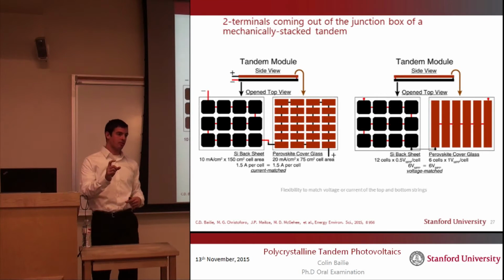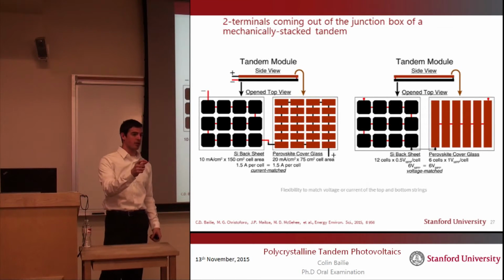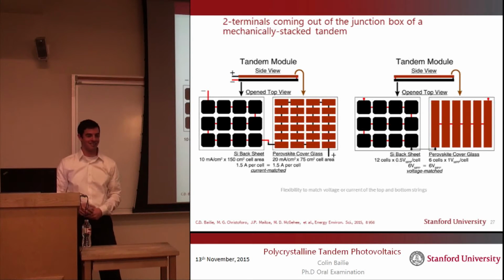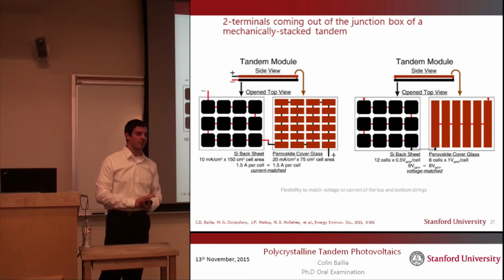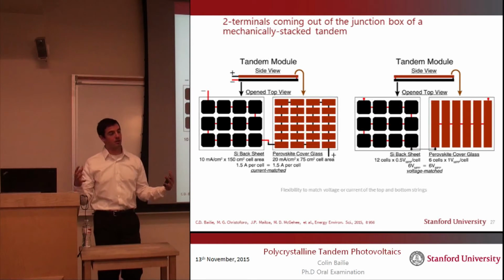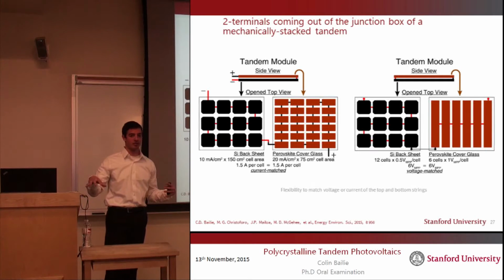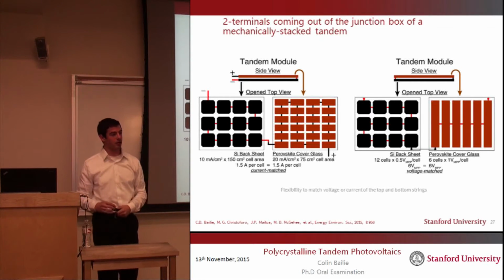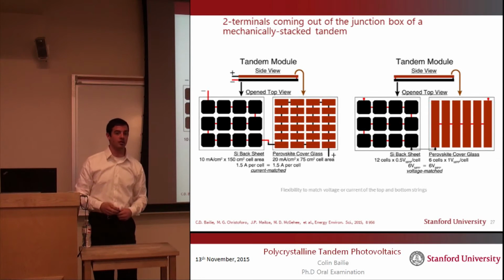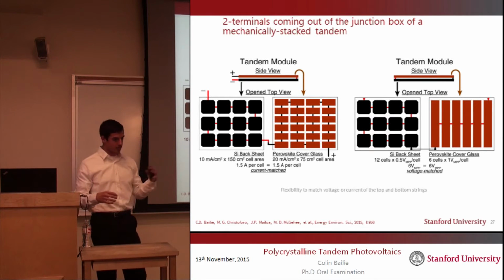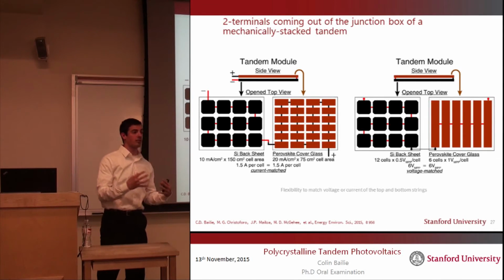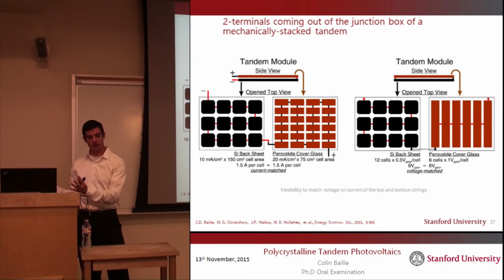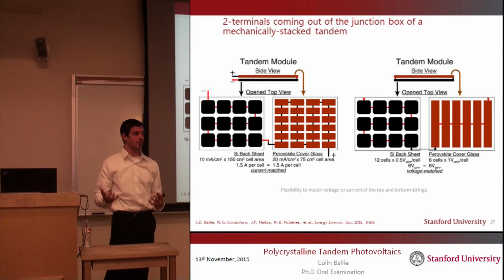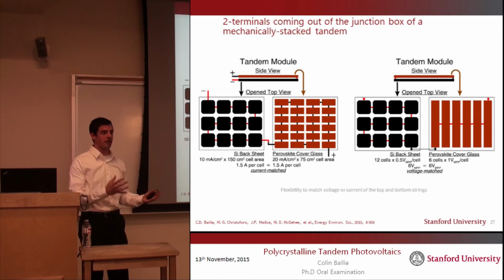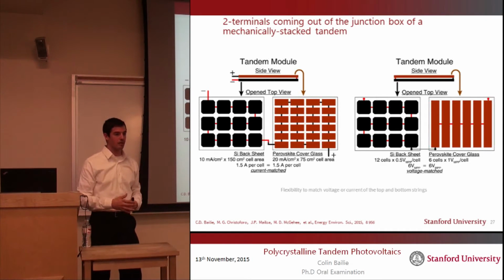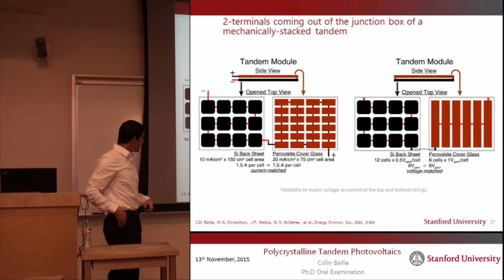Now, the way I tested this was to separately test the perovskite cell and then separately test the silicon cell. And if you took no imaginative leaps, then when you make your module, you will also have to separately test the perovskite and the silicon, meaning you will have to have 4 wires leaving your module, and then you will have to have 2 inverters that are associated with that module. And the common argument against mechanically stacked tandems is if you have to do this, then you are adding significant extra complexity and cost to the system, to the installation, and that at the end of the day, you're behind from where you might have been with just a single junction cell. But that's not actually the case.